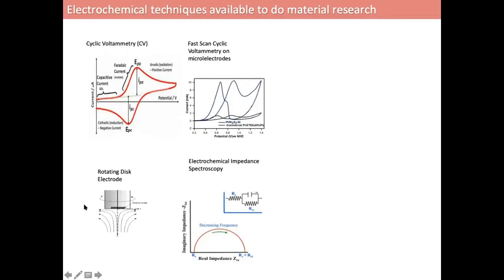The third technique normal people use is the rotating disc electrode, where the electrode is not stationary. It is rotated at a known RPM, and we can adjust the hydrodynamics across the electrode-electrolyte interface. The application of such a technique is that one can measure the rate of charge transfer across the interface. Okay, this is a very important technique to study the ORR reaction, OER reaction, or hydrogen evolution reactions. Here, in all three techniques we use DC bias on the electrode.